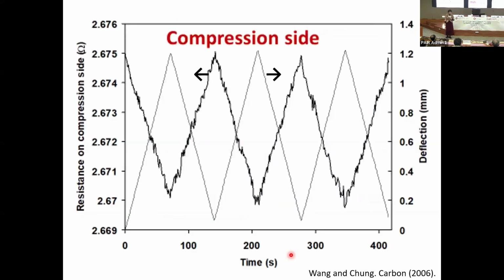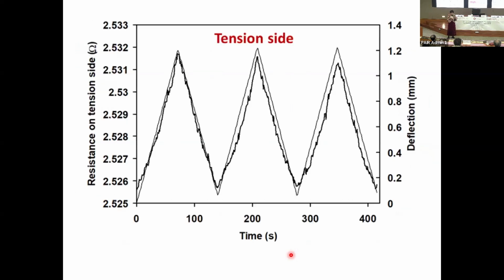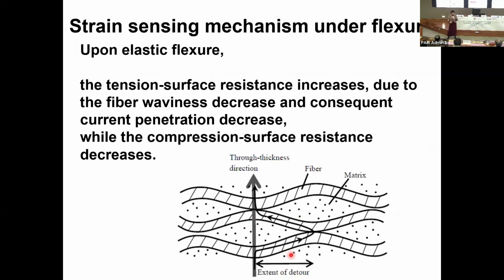And this is the compression side's surface resistance, shown in thick line. And every time one flexes it, that compressive surface resistance decreases quite reversibly. In the tension side, it's just the opposite. Okay? The reason is that for the tension side, the resistance increases due to the fiber waviness decrease. That is, you're kind of stretching it. So the fibers become less wavy, and so less touching between the fibers along the vertical direction. And so the current penetration decreases, and thereby the resistance increases. And the opposite applies for the compressive surface resistance.